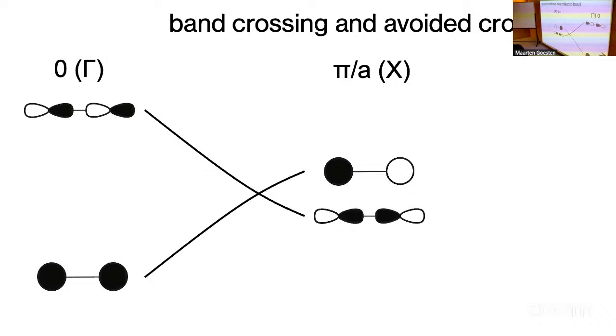But one of the main typical mechanisms is an avoided crossing. So let's say that we have this chain of s orbitals, which we know goes up in energy. We also then can introduce a set of p orbitals that are translated. And we know that actually for that, the energy goes down. So normally, these two bands, they would cross. But by virtue of the Wigner-von Neumann theorem, it prescribes that two bands can only cross in the presence of certain symmetry operations. In this case, s and p orbitals are symmetry